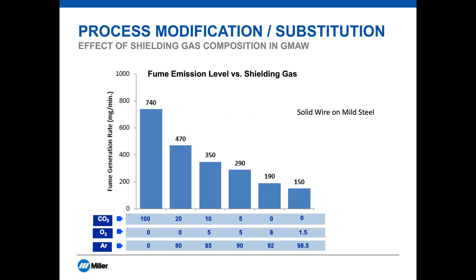This slide shows the effect of shielding gas on fume generation rate for gas metal arc welding. The results are similar for flux cored arc welding. The bottom line is that the less active the shielding gas is, that is, the higher the argon content, the lower the fume generation rate will be.